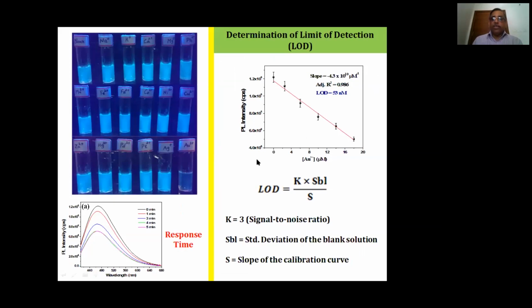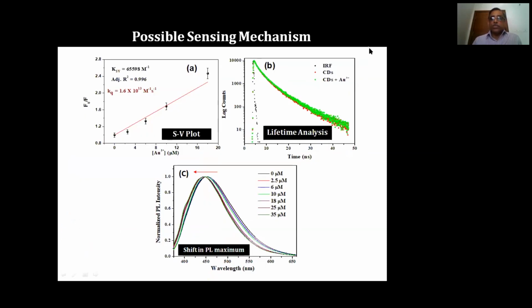Now, limit of detection is still lower than what we got with the earlier material - the limit of detection is almost 50 nanomolar for detecting gold in solution. So this is how we can see that different sources, different functionalization, different doping, vary the property of the carbon dots, and that helps us use them for different applications.